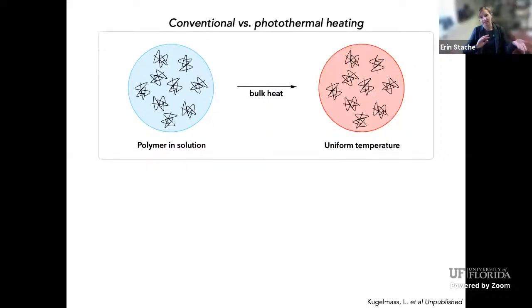And so we compare the ideas of bulk heating. This is taking something in solution or in solid phase, giving it enough energy that everything, including its surroundings, gets up to temperature. So if you're running a reaction at 100 degrees C, it's not just your reagents that are at 100. You need the solvent to be at 100. You need the oil bath to be at 100. You need everything to get that hot.